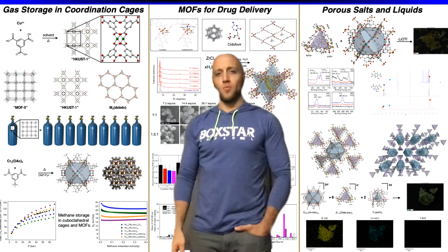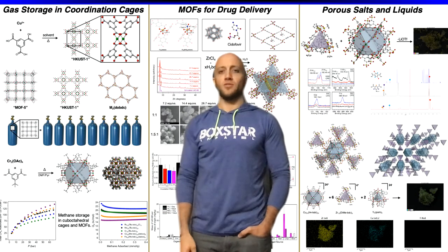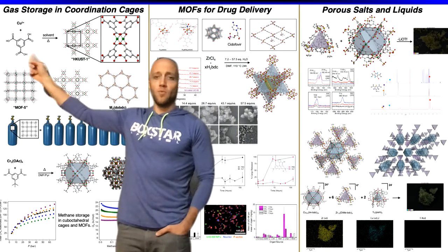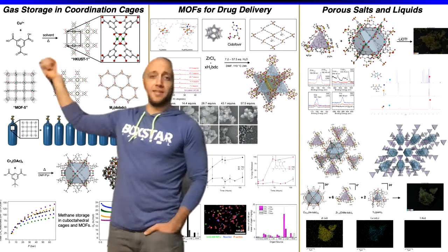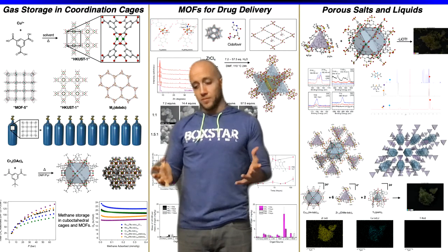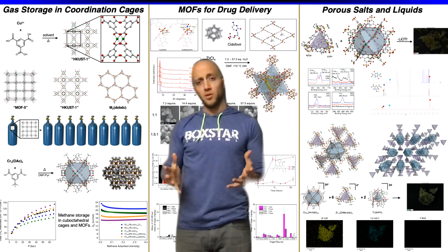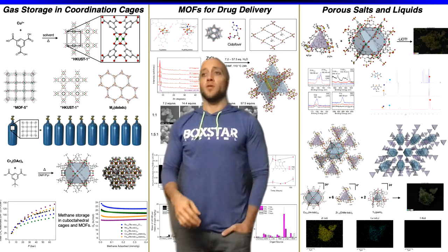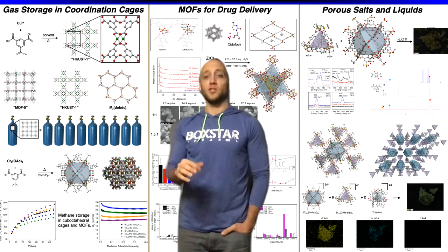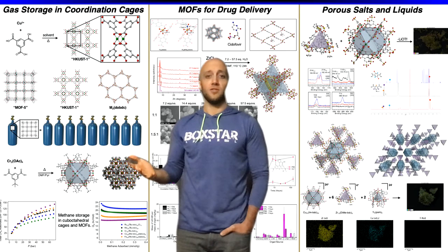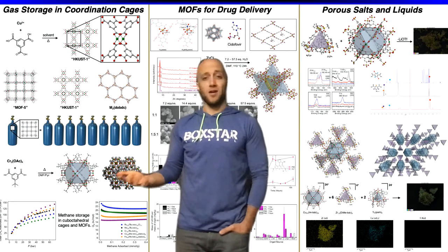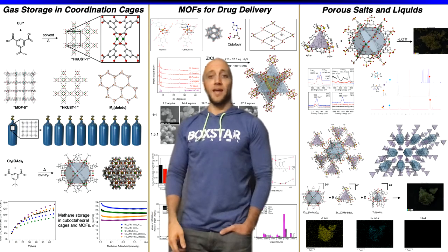So metal organic frameworks, or MOFs, are these three-dimensional structures based on a metal cation and some organic bridging linker. You react these together and form a three-dimensional structure. So the structures can be very tunable, with very high surface areas. You can put functional groups on the organic linkers that are in these structures. You can change the metals in these structures to change their properties. And a very common application for them, because they're such high surface area, is gas storage.